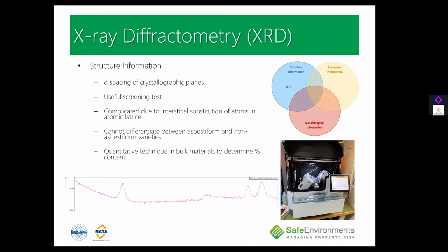X-ray diffraction has been a popular technique in the detection of asbestos in vinyl floor tiles. An example of a spectra is provided below, showing peaks which are consistent with the presence of chrysotile at about 12.2 and 24.4 degrees 2 theta. So the correct interpretation of this result is that the presence of chrysotile cannot be ruled out, but there simply is not enough evidence at this stage to unequivocally say that the material contains asbestos. This is also because X-ray diffraction will detect non-asbestiform varieties and similar materials that may provide similar spectral peaks.